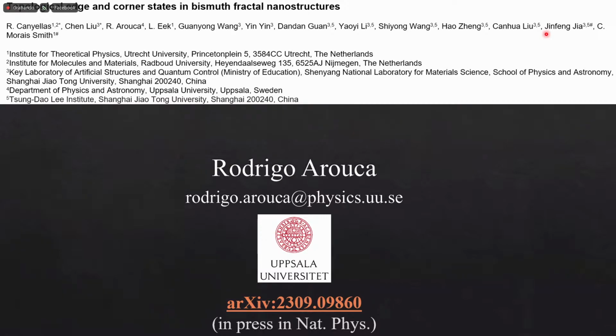They had a previous paper where they showed this, but something they did not publish were some measurements they did of the electronic density in these systems. They actually saw some features there that I will try to convince you are signatures of a topological phase in these materials. This started, as I mentioned, during my PhD, and then we tried to do the modeling of these materials.